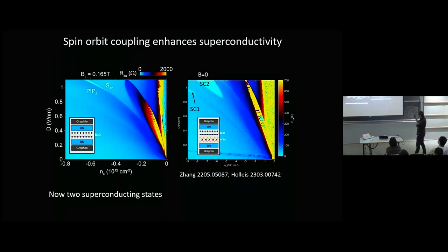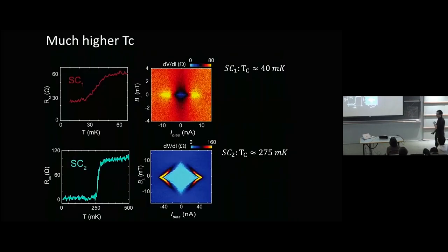So we, in collaboration with them, started to look at some of these samples a little bit more closely, in particular focusing on the strongest spin-orbit samples that you could find. And you find that indeed there's this large superconductor that they found, and there's indeed another superconductor, and it indeed seems to help. I'm not going to make it to the spontaneous spin-orbit coupling, but I'll finish this part.